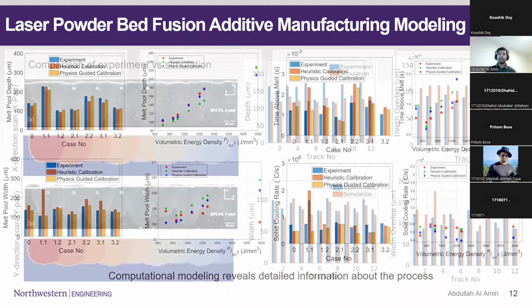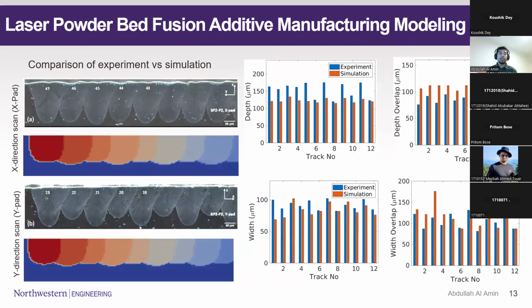In a similar fashion, there is also the multi-track case, not only one line of scan. This is basically a cross-section, and you can think of the laser scan directions as coming out of the plane. It comes from behind, comes out of the plane, and goes from the back of the screen toward the front. There are multiple tracks, so can we model them and also estimate the depth and width of those particular scans? With our computational code, which relies on the finite volume method, yes, it can. And as you can see, it does compare pretty well.